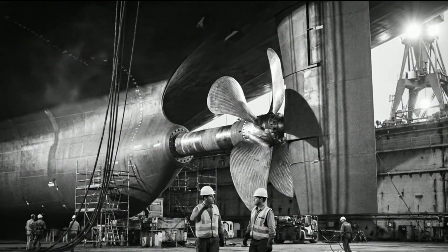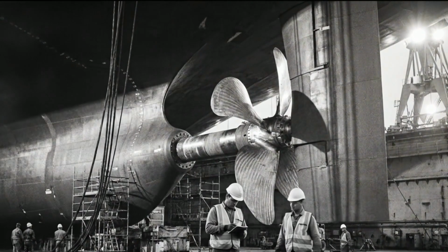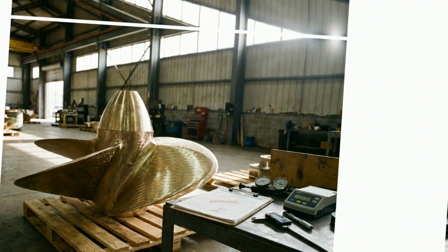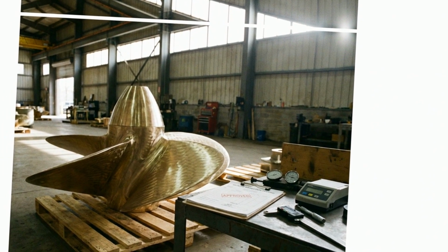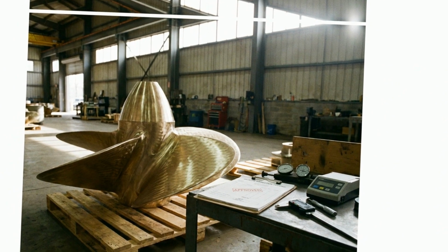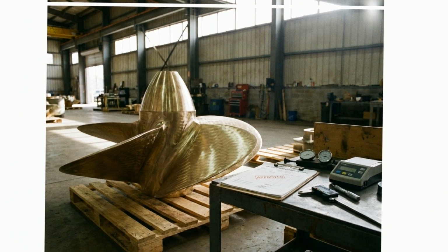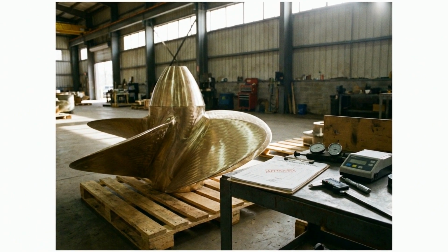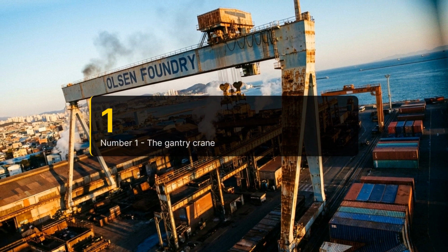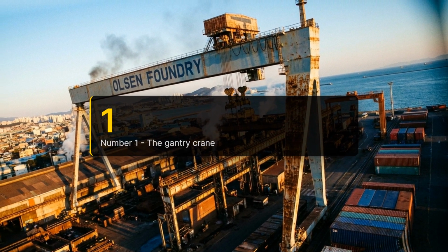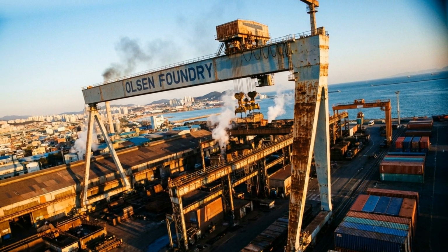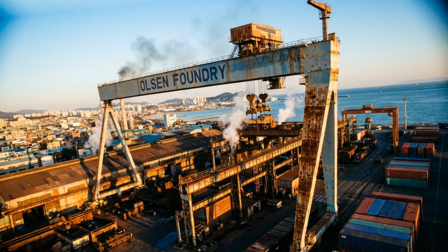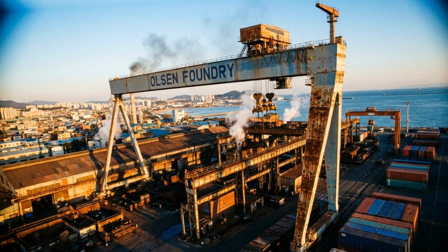The propeller that comes out of this process will turn at roughly 80 to 100 revolutions per minute for the operational life of the ship, perhaps 25 years of continuous service, crossing oceans, running in conditions from flat calm to severe storm seas. It was cast in one pour, cooled over weeks, machined to 2mm tolerances across 10 meters, and balanced to within kilograms. If it's wrong, the ship tells you, immediately, and for as long as it runs.